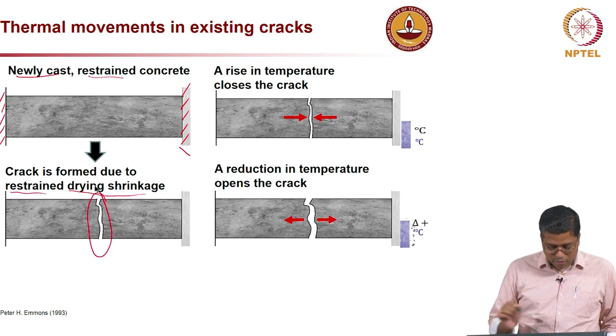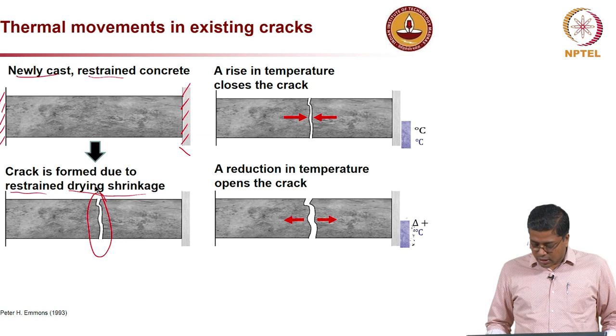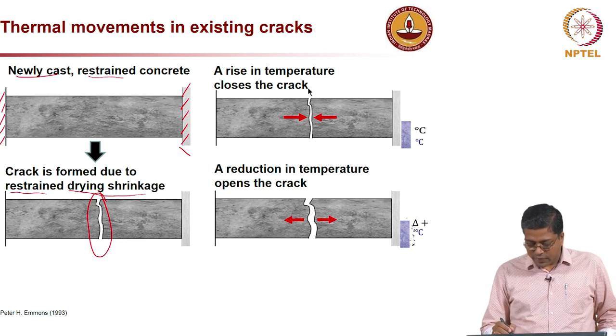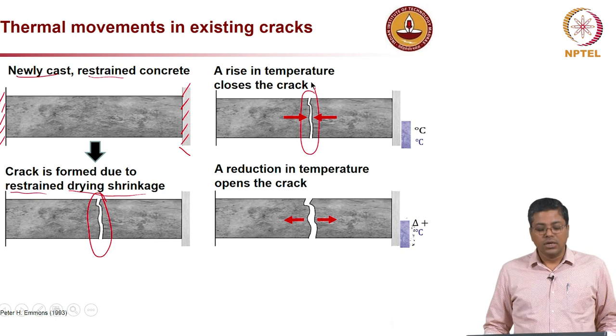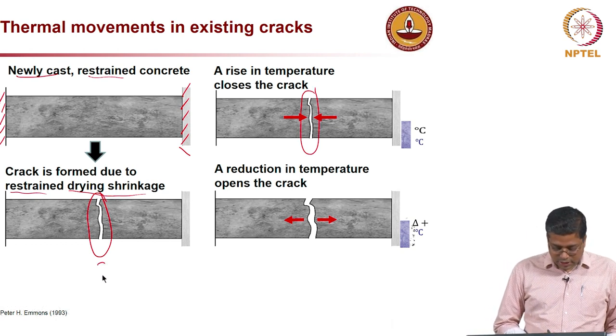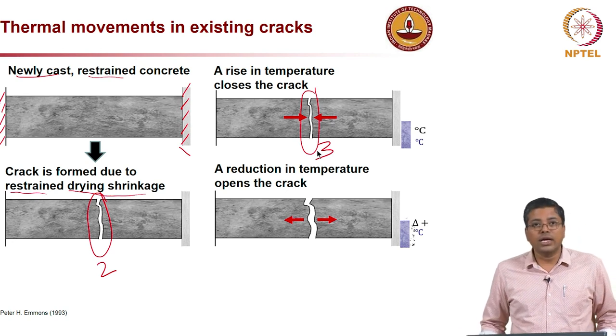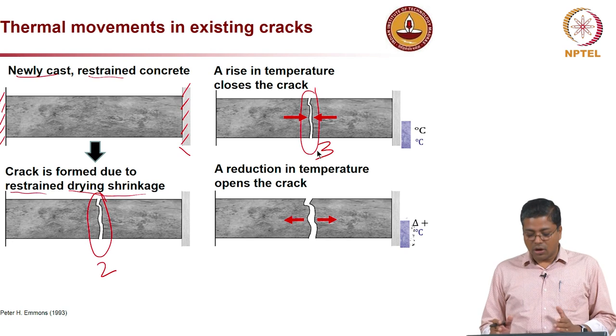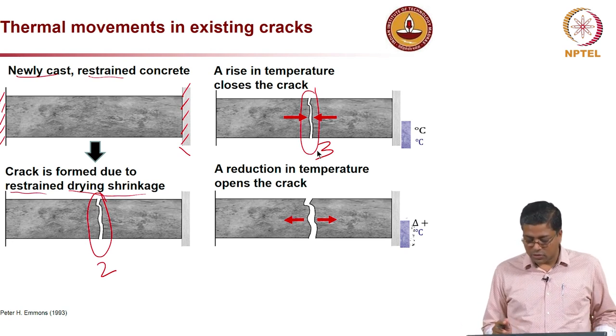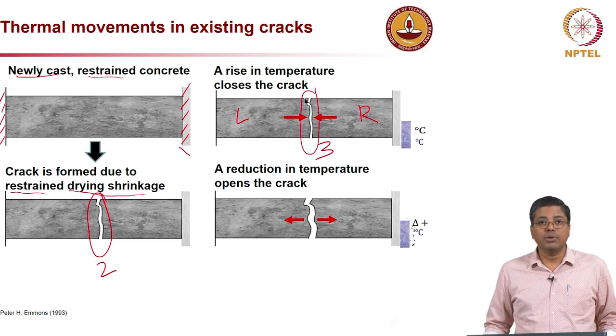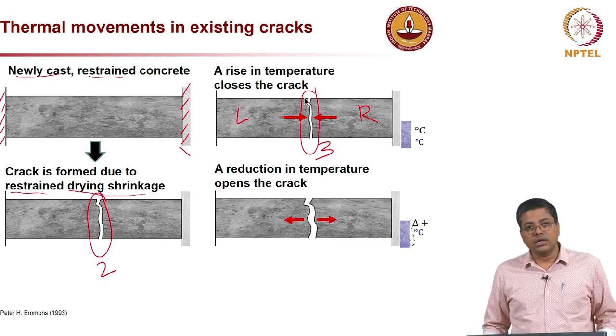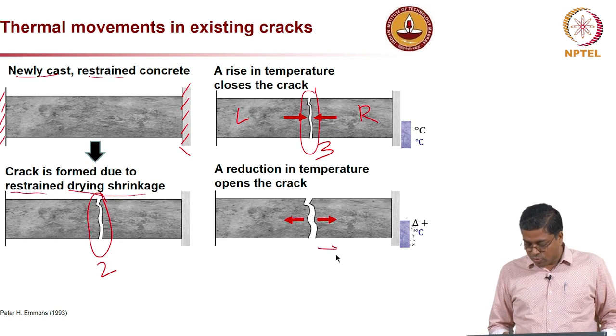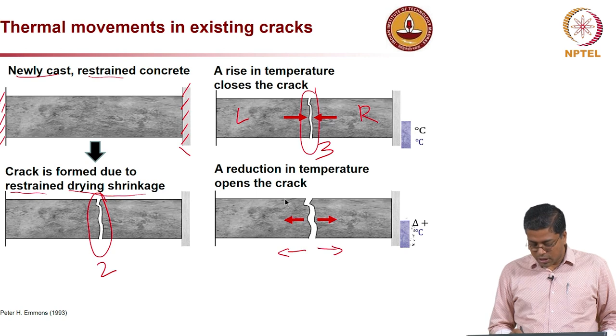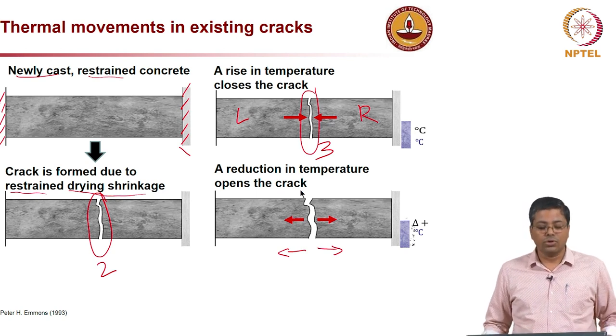So, you can see the crack forming almost at the center, and on the right side image you can see that once the crack is formed, if there is a rise in the temperature, this crack width decreases. So, comparing to the second step here, in the third case you have a reduction in the crack width, because the concrete is going to expand. So, the concrete on the left and right side is expanding, and the crack is being closed. Now, what will happen if there is a reduction in the temperature? The same concrete will now move outward, or in other words, it is shrinking. Both left and right side concretes are going to shrink, and then it is going to open the crack.